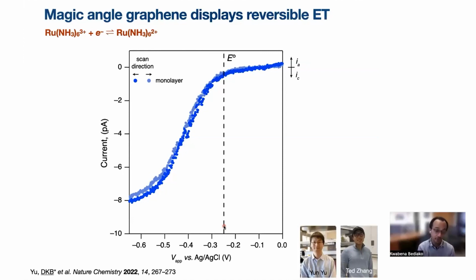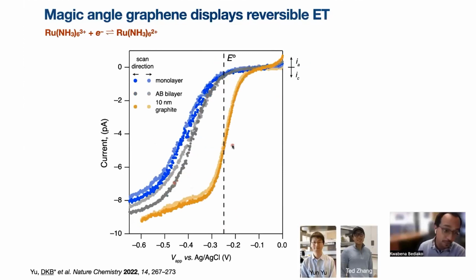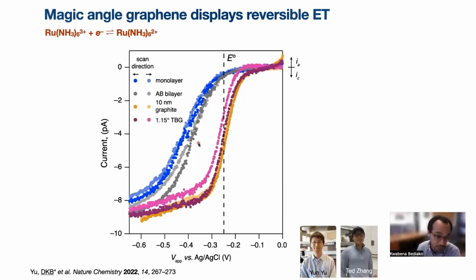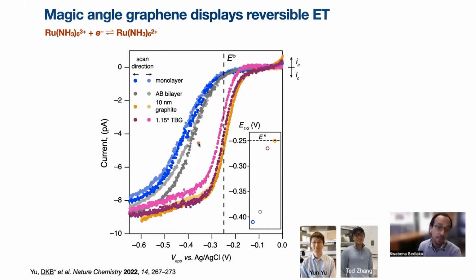As we go to bilayer graphene, we have more density of states to work with, so that increases. And if you were to go to bulk graphite or a piece of platinum or gold, you see that now your voltammogram is straddling this E naught, which means that it's a reversible reaction. So what happens if we take two layers of graphene, but instead of having them Bernal stacked, we twist them so that they're at about 1.2 degrees? Well, now you find that they behave for all intents and purposes like bulk graphite. Electrochemically, they're behaving reversibly. That was our first hint that our hypothesis that twisting can control the rates might actually lead to something.